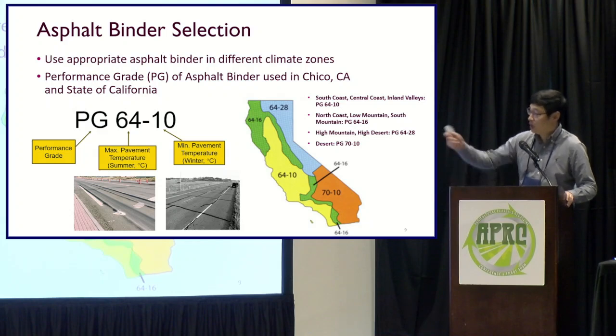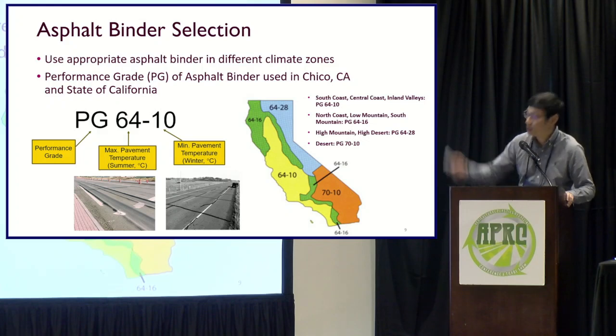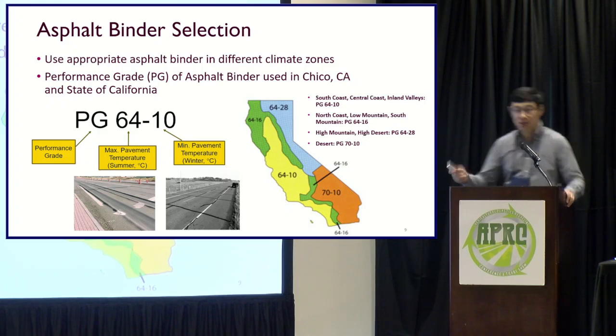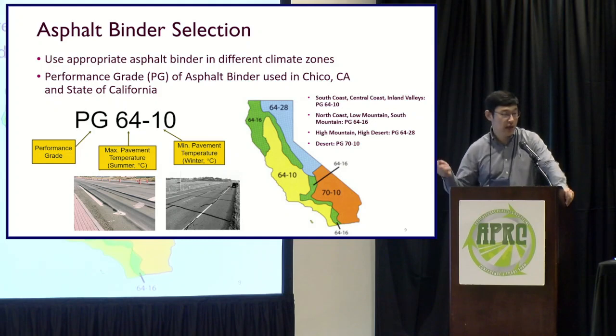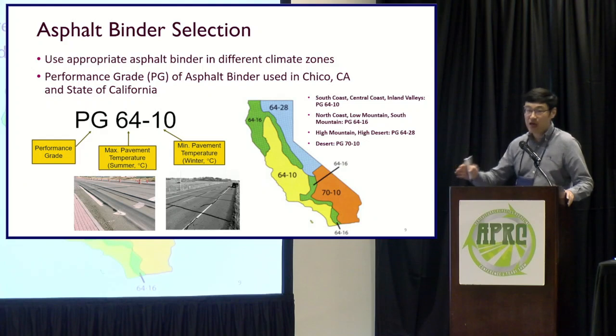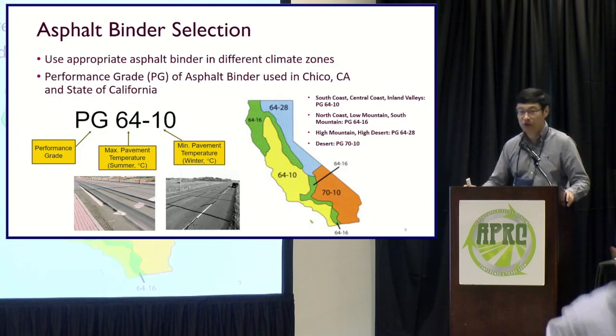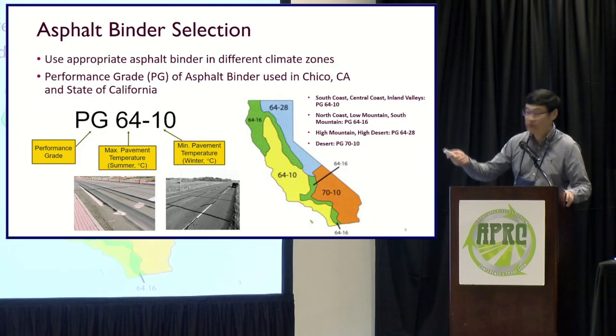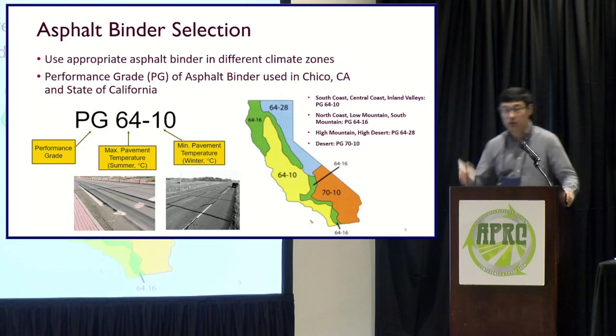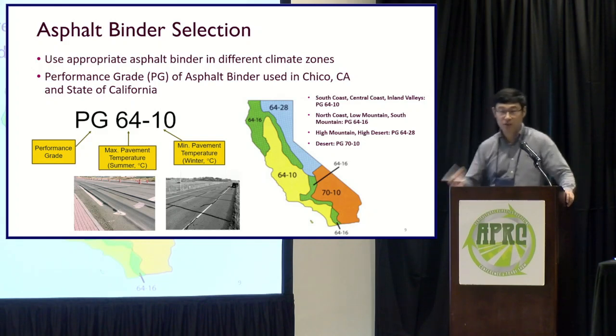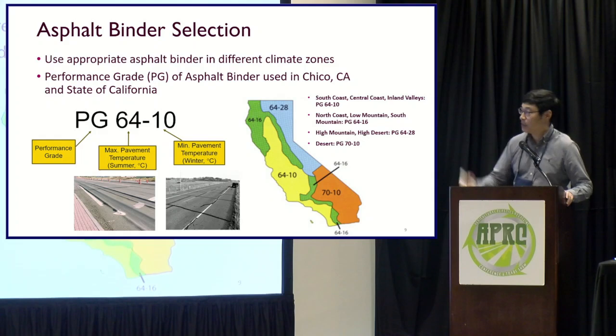For example, for the binder used in Chico, California, we use a PG 64-10. So PG stands for performance grade. The first number, 64, means this type of binder can be used in the area where in the summertime, the pavement temperature can be as high as 64 degrees Celsius. That's the first number, 64. -10, that is the lower temperature in the wintertime. The pavement temperature can be as low as -10 degrees Celsius. So one is high pavement temperature. The other one is low pavement temperature.